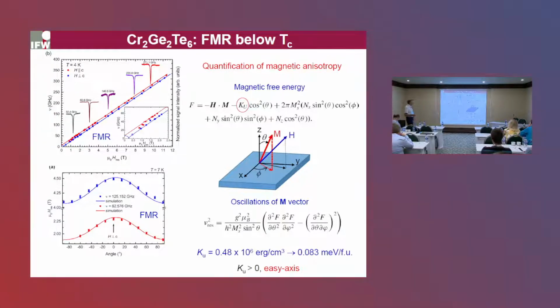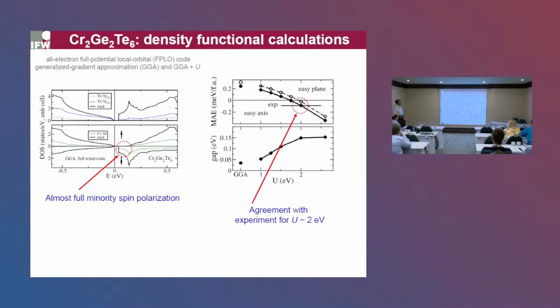And the free energy is composed of 3 terms. This is the Zeeman energy, the intrinsic magnetocrystalline anisotropy, and also the so-called shape factor, which is due to the specific plate-like shape of the crystals. From this, we can accurately calculate the magnetic anisotropy energy, which corresponds to about 83 microelectronvolts per formula unit, and the sign is positive, so that means it's definitely easy axis, which is required for the stabilization of magnetic order in the single layer limit. So how reasonable is this number? The theory helped us in this context.